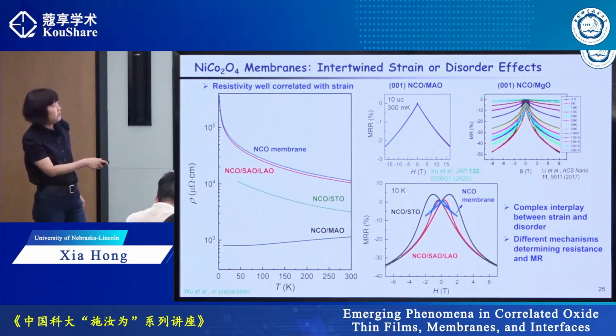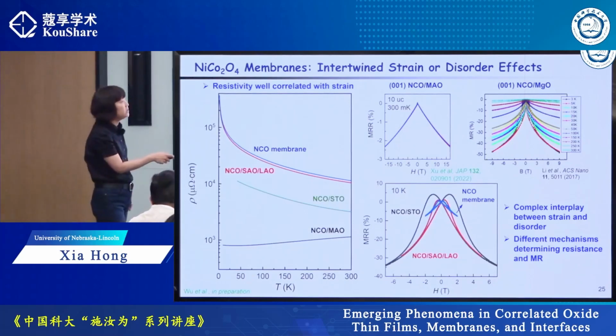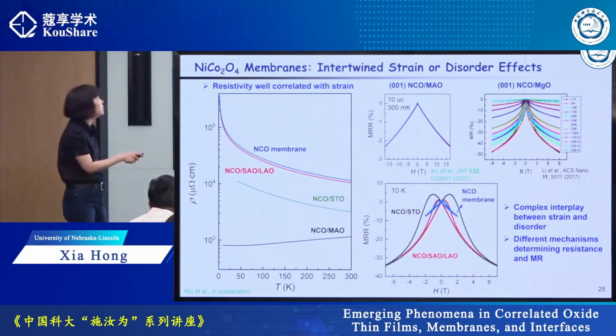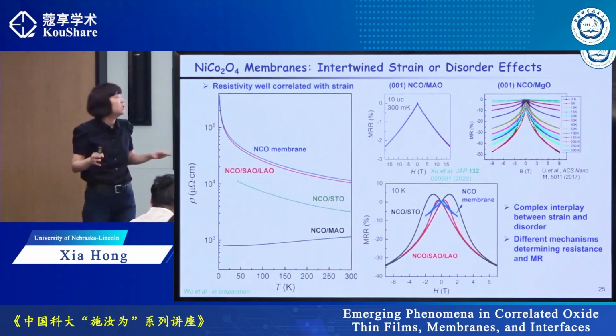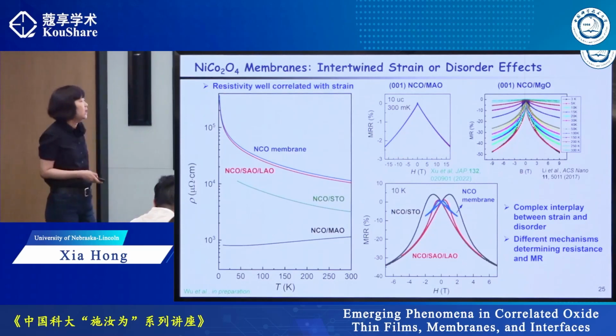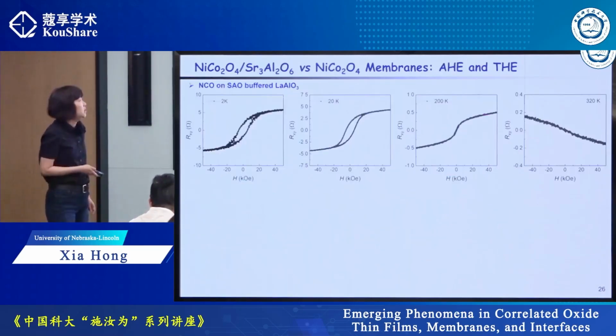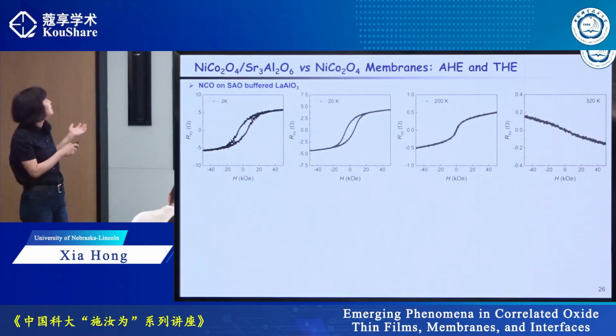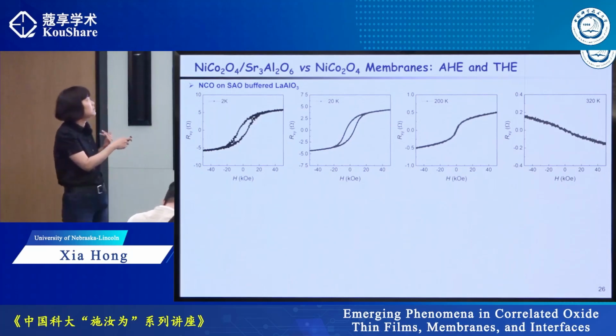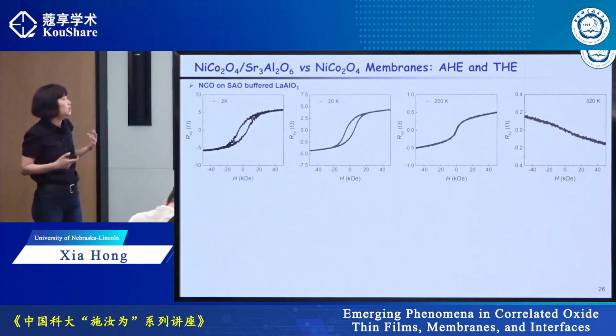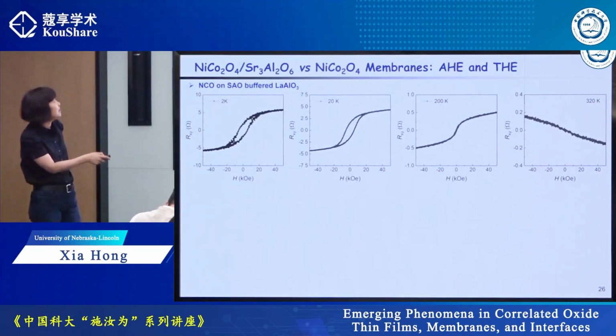What is interesting is this one is epitaxially grown on strontium titanate, so it's not lattice matched that well. And this blue one is the NCO membrane. So NCO membrane, even though it's more insulating, its magnetoresistance is more linear-like, and it has smaller magnetoresistance. So it tells us that there are different mechanisms contributing to resistivity and magnetoresistance. So now what we did is study the anomalous Hall effect in it. This is before water etching, NCO is epitaxially bonded on the substrate. If you measure the anomalous Hall effect, again, you would see this non-monotonic temperature dependence. There's a sign change. The hysteresis is no longer very squarish, meaning you probably have canted spin.